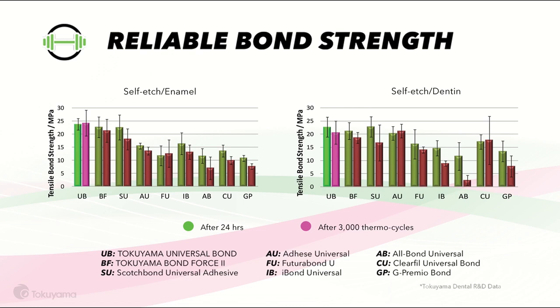Reliable bond strength. Tokuyama Dental's research and development team in Tokyo performed a study comparing Tokuyama Universal Bond to other leading brands, listed below the graphs. The first 2 charts we're seeing are comparing the bond strength in self-etch mode to enamel and dentin. The green color shows the bond strength results after 24 hours, and the pink color shows results after 3,000 thermal cycles. Looking at the charts, we can see that after 3,000 thermal cycles, Tokuyama Universal Bond continues to provide one of the highest bond strengths.